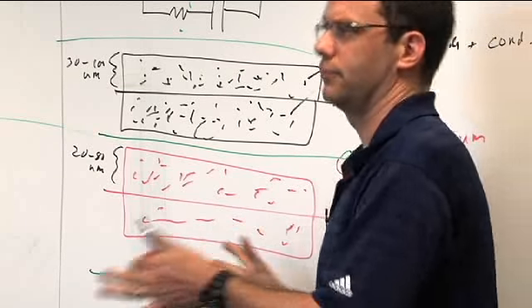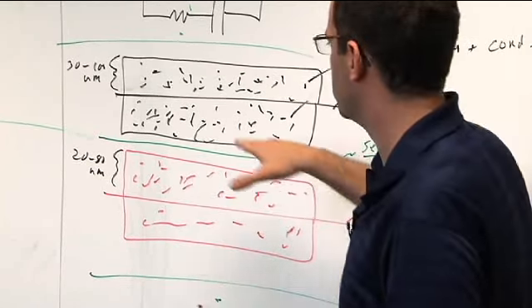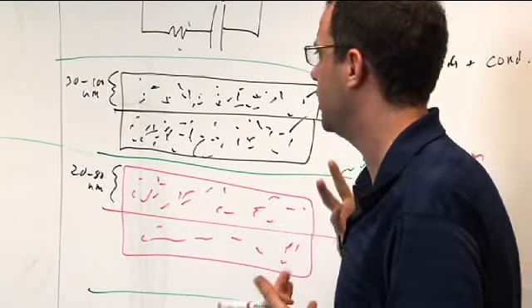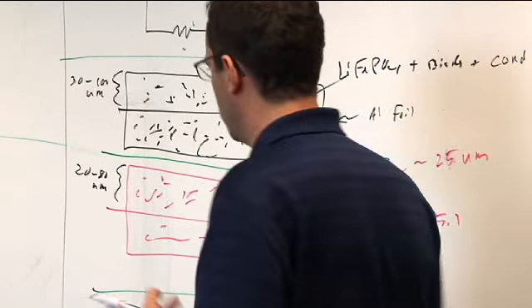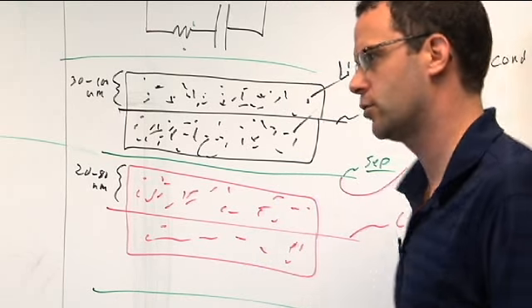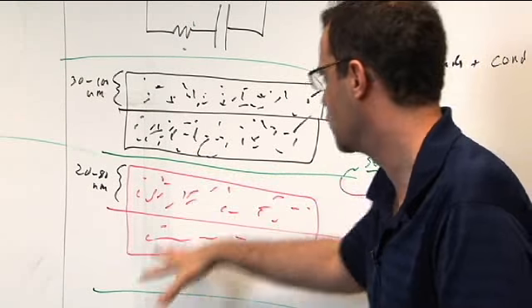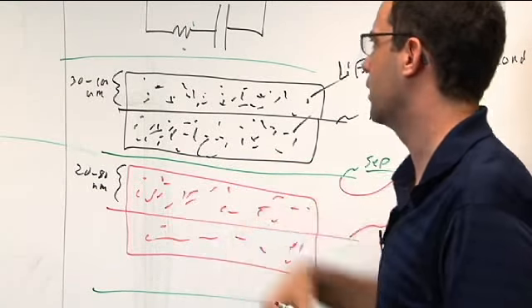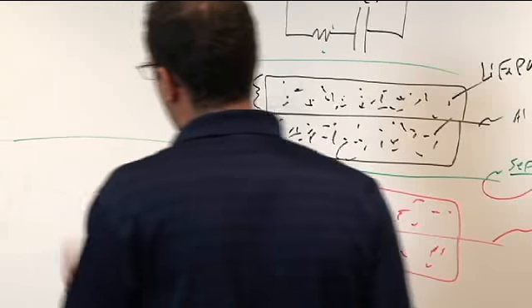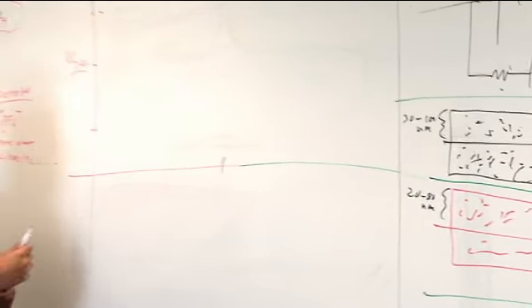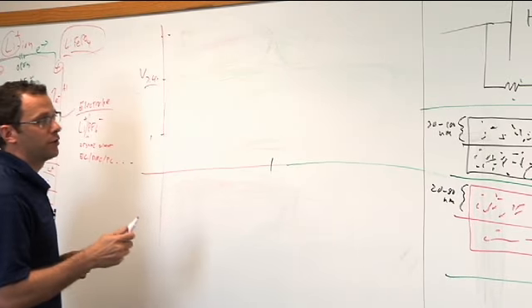wiggle room in here. These things are unlike a lead acid battery, which is like kind of sloppy inside, or you can shake it. These are what we call starved systems, where there's no free liquid inside of them. If you cut up a lithium-ion battery, you can't squeeze out electrolyte. It is fully infiltrated and absorbed into either the separator or the electrodes. Okay. And you don't want to put too much in because it's expensive stuff, so you want to have just enough. Okay, so now we can talk about some things that are probably more interesting to you.